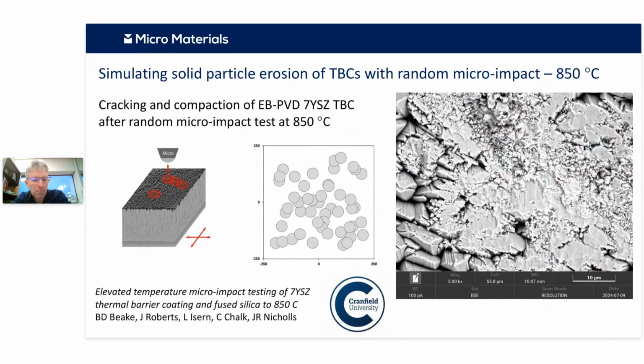So more recently, we've started to play around with high temperature impact testing. One of the things we've been doing, as James mentioned, is that thermal barrier coating systems are quite an interesting thing to look at. And we've done our so-called randomized impact tests. In this case, we're doing a cyclic test, but between each impact, we're moving the sample in a designed, programmed array. There's just one example shown in the middle, and that creates this high temperature damage.